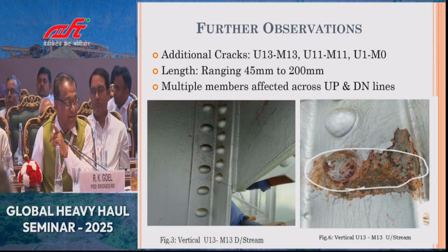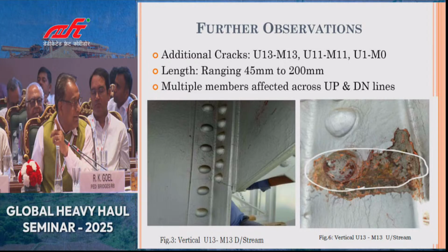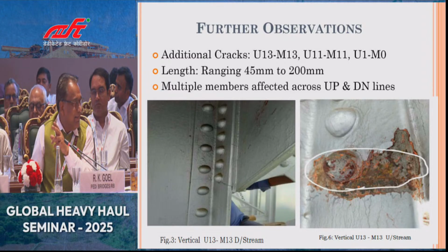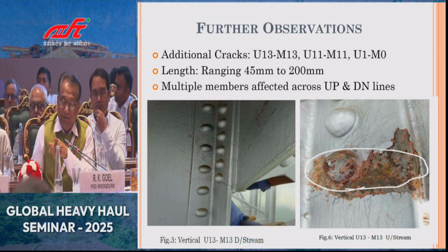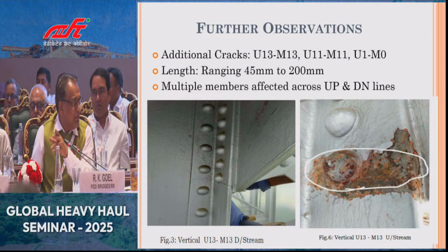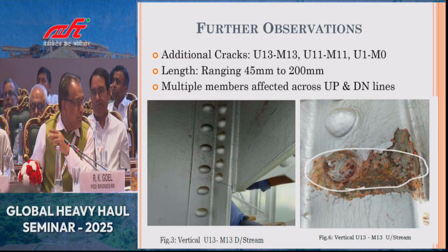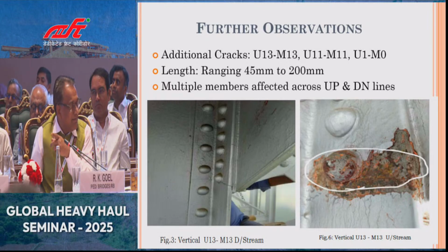And we have detected 27 more cracks in other verticals. That basically validated our conclusion that it is a fatigue failure, and if these cracks had not been detected, there would have been more failures in the rest of the girders also. So speed restrictions were imposed, and the train loads which were permitted were also reduced to sustain the traffic on this important route.